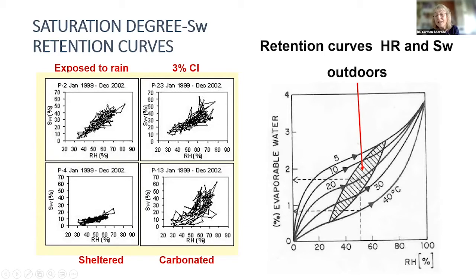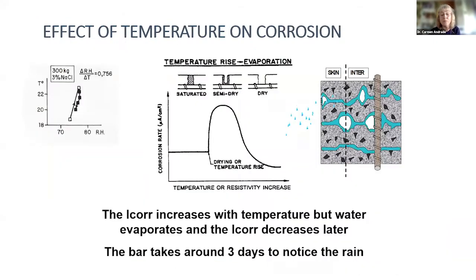In that case, temperature is a key parameter when we have concrete in the open atmosphere. And this has been plotted and studied by our colleagues with atmospheric corrosion. When you increase the temperature, you have evaporation, and after some time there is a decrease because you have completely evaporated the water. In that case, at the beginning of the temperature increase, there is an increase of the corrosion rate, but after there is a decrease. And that is why it is so complex to interpret what is happening here, because we have the skin and the interior, and this is a continuous opposite process that makes the modeling very difficult.